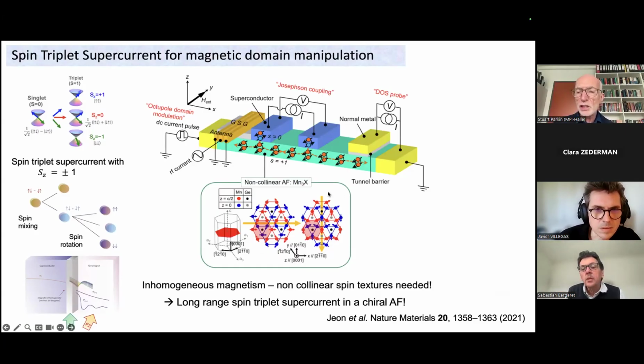This is manganese-3 germanium, and that structure has manganese moments, shown as these blue and red dots, separated by, in this case, germanium. And this forms a so-called Kagome lattice. This Kagome lattice has many interesting properties.